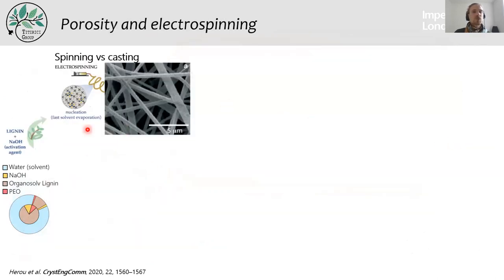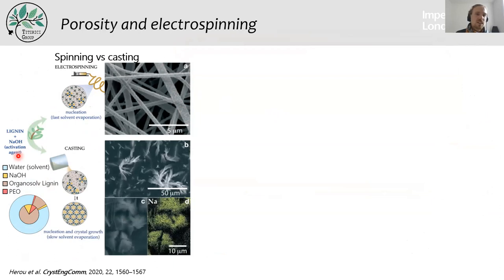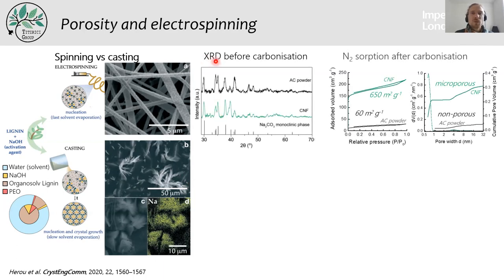So we've been looking at why these fibers are particularly interesting. If you spin them, you can see on the surface all of the little sodium hydroxide crystals. They're approximately between 60 and 80 nanometers. And basically, if you take the same spinning solution, but instead of spinning it, you just cast it into a Petri dish and let it dry, then if you look at here are the EDX and the SEM pictures, you look at these crystals, they are approximately between 10 and 50 microns. And that has a massive influence on the properties. We performed XRD before carbonization, and you can see the characteristic monoclinic phase here of sodium carbonate. So basically the sodium hydroxide carbonates directly as soon as it's in contact with air.